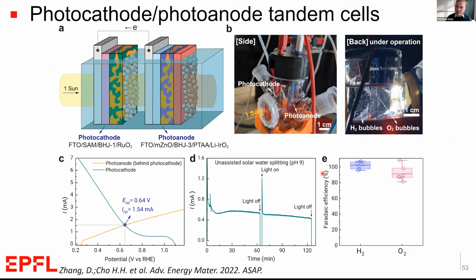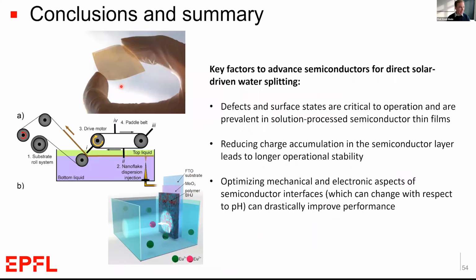However, this first demonstration still had a relatively low solar to hydrogen conversion efficiency of only about 0.5%. So there's a lot of work that needs to be done on this sort of concept to get this to work at 10%, which we would need with also more than a year's stability to give it some reasonable commercial viability. But that means there's a lot more work for us to do in our lab.